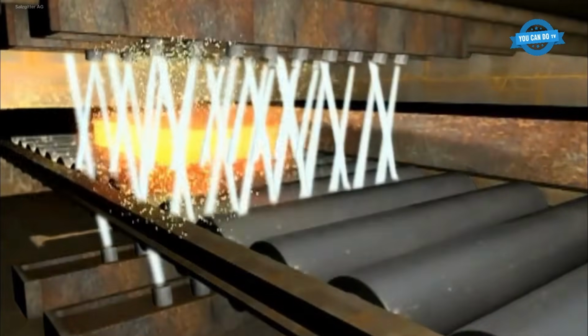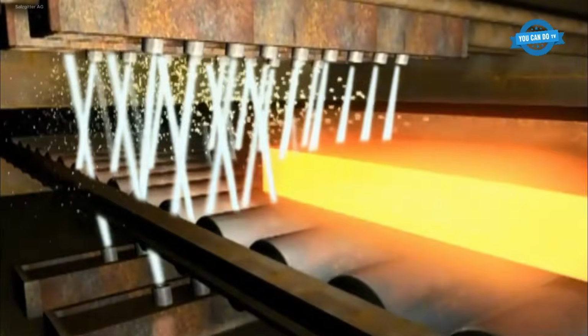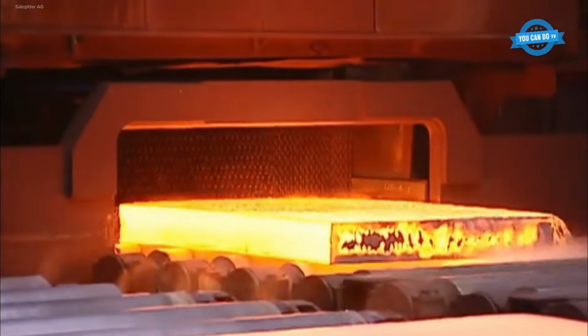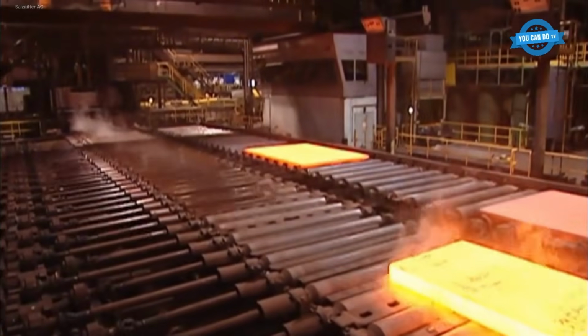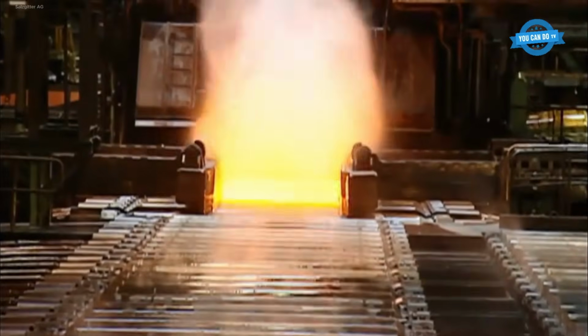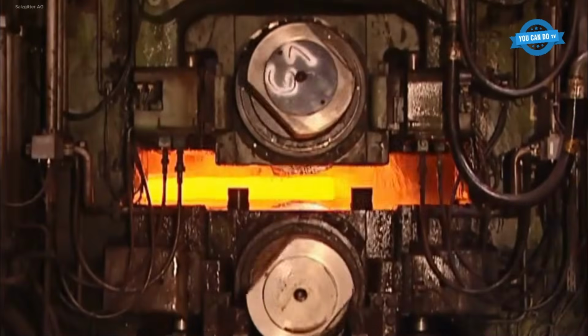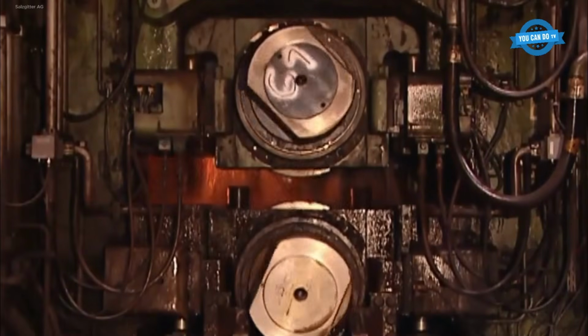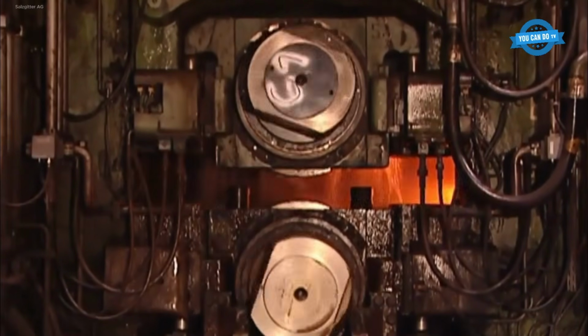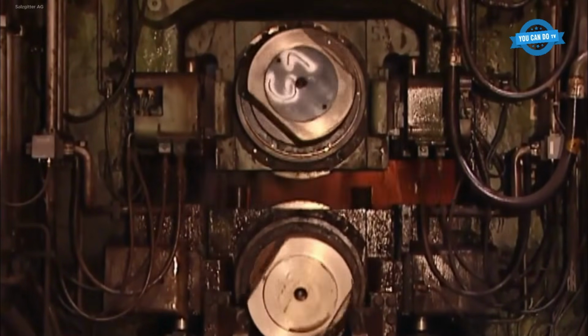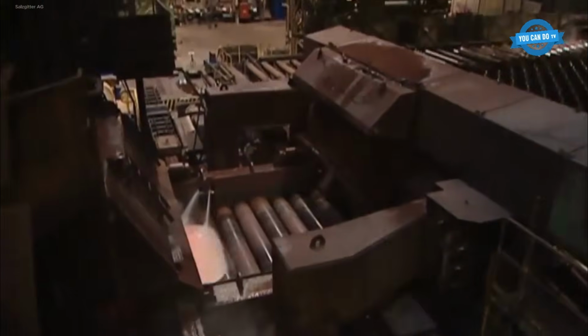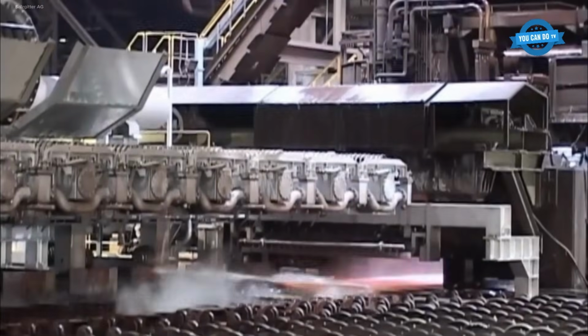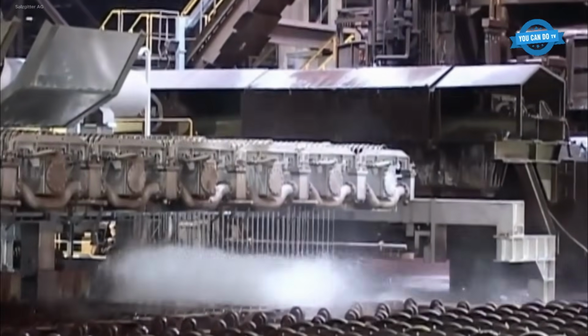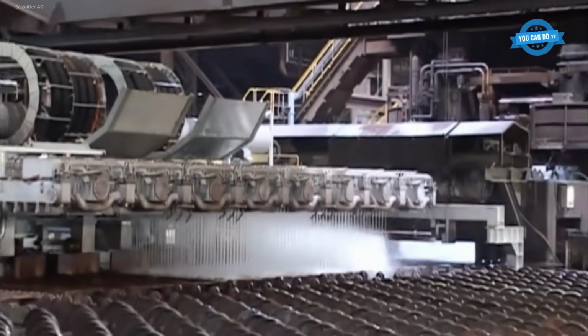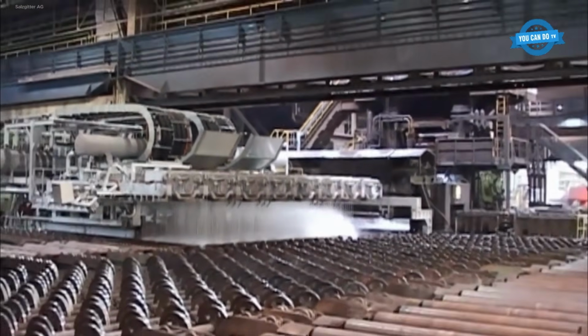Descaling spray systems operating at 200 bars clean the slab surfaces before rolling. Automated rolling schedules consider slab temperature, steel composition, and desired final dimensions. Following hot rolling, accelerated water cooling is employed to tailor mechanical properties, all managed through a central automated system. After cooling, plates undergo ultrasonic testing for internal defects, then marking, trimming, and sample extraction for mechanical and impact testing.